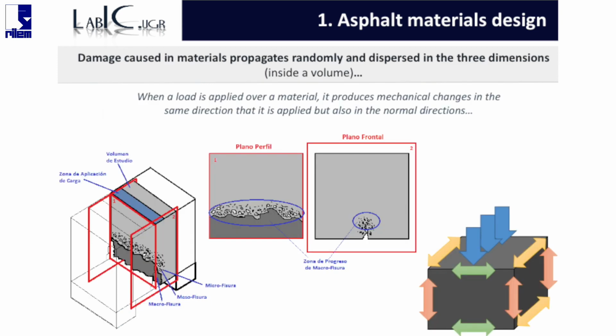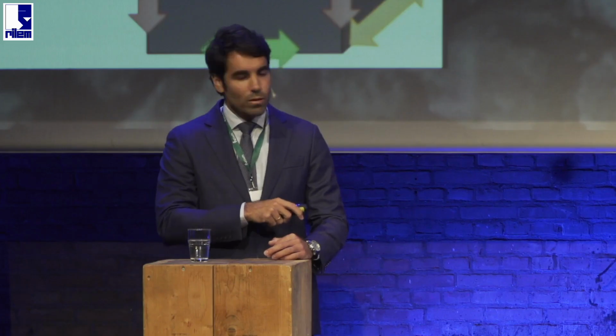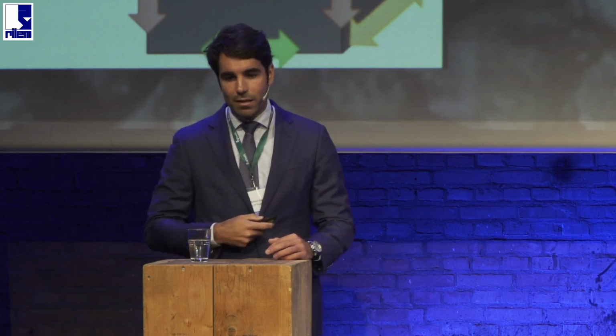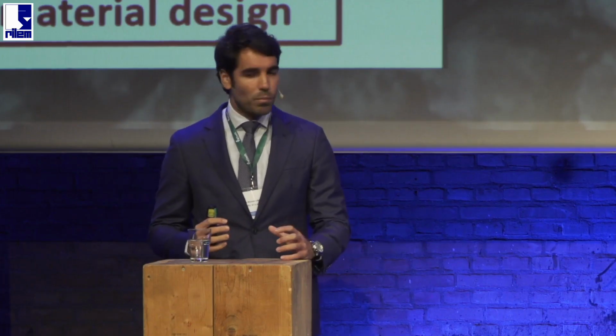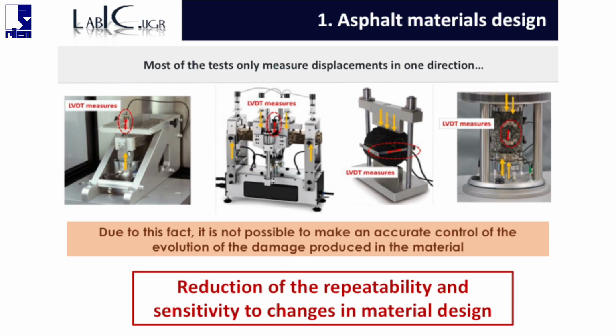Materials do not have a unidirectional propagation of damage. When you apply a load over a material, the material will respond with mechanical change in the same direction of the load, but also in the normal direction. And because of this fact, damage propagates randomly inside the volume of the material. Nonetheless, most of the tests measure the change produced in the material just in one direction. Because of this, it is not possible to have an accurate measurement of the propagation of the damage. These aspects reduce the repeatability of the test and also reduce its sensitivity to the change on the material design.